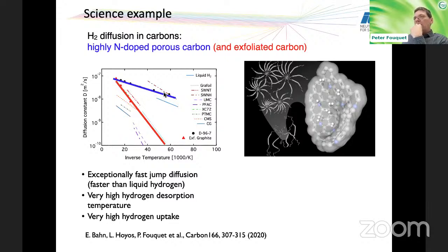And you see that the mobility is very, very strongly enhanced for this one, making it a very interesting storage material. You also have a very high hydrogen content for them. They can take up a lot of hydrogen. And you see this here compared in this plot of diffusion constant versus inverse temperature.